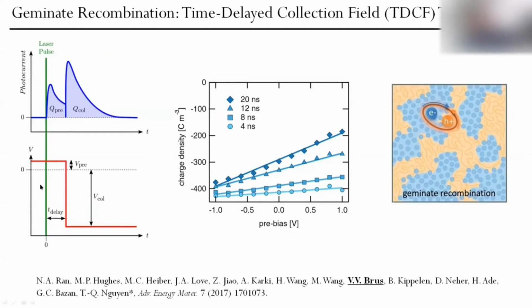So since we know the number of photons in this pulse of laser, by comparing the total number of photons to the total number of extracted charge carriers, we can determine the geminate recombination prefactor, a coefficient which shows which fraction of excitons is split into free charge carriers.